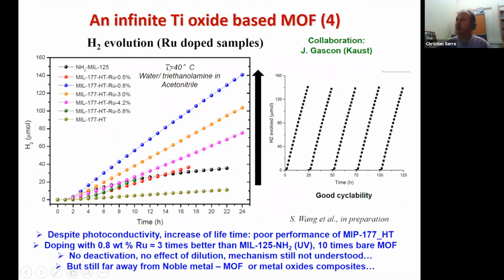And now for hydrogen evolution, this material was tested, with different amounts of ruthenium and in comparison with both the bare titanium chain-based MOF and also the benchmark NH2-MIL-125. You can see here that, first of all, it was quite disappointing that the pure titanium MOF, although irradiated under UV, was less active than the NH2-MIL-125.